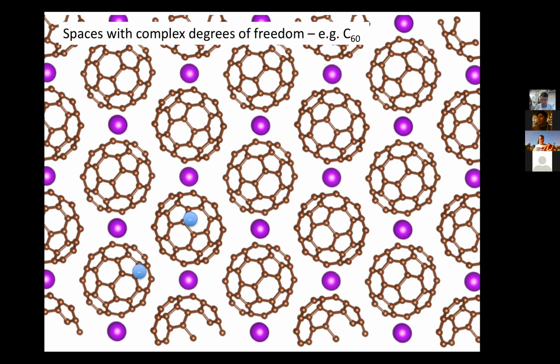And this is an insulator in the pristine case, but you can dope it by introducing alkali atoms. So the purple atoms are supposed to be alkali atoms, and they contribute an electron. And at half-filled doping, if you associate 3 charges for every C60 molecule, you get superconductivity. And that's what we discovered in 1991. We discovered superconductivity in C60, which was at a much higher temperature than graphite. And this was a very intense year.